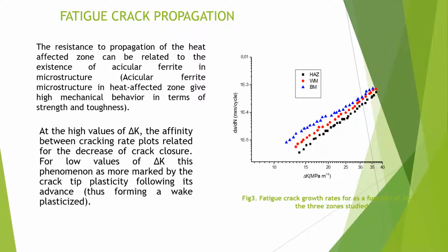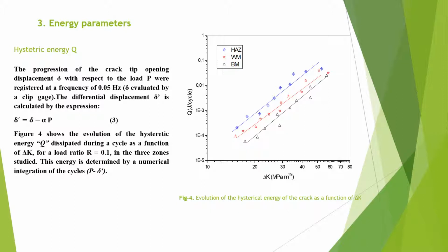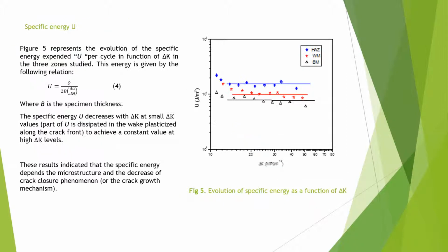thus forming a wake plasticity. For energy measurement, we noticed that the hysteretic energy Q increased when delta K increased for the three zones studied. The energy Q is usually dissipated in the plastic zone. The specific energy U decreased with delta K at small delta K values.